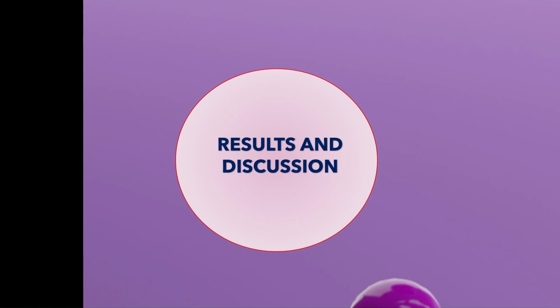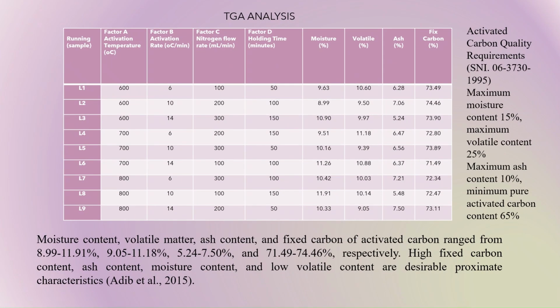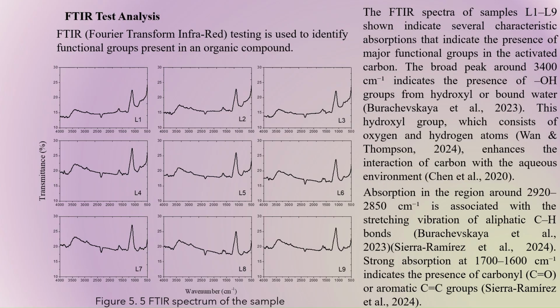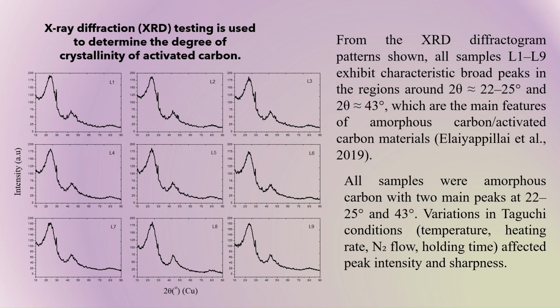Results and discussion. TGA results indicate low moisture, ash, and volatile content, along with high fixed carbon, confirming good quality activated carbon. FTIR spectra identify functional groups such as hydroxyl and carbonyl groups, which enhance interaction between activated carbon and methylene blue molecules. The XRD patterns reveal characteristic amorphous carbon peaks, confirming porous activated carbon structure.